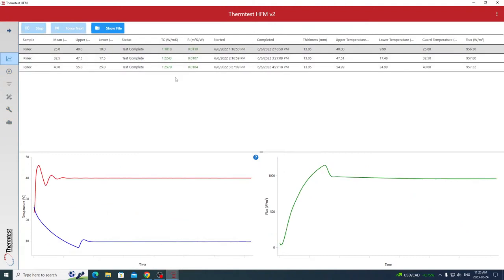So here's Pyrex run at 25 mean, 32.5 mean, and 40 degrees mean. We have values of 1.18, 1.22, and 1.25, and that comes from the resistance and the measured thickness of the sample. And there's your upper plate and your lower plate for each of these, and the guard temperature. Of course, the guard temperature is set to the mean temperature. So you can see that's why we're getting high confidence values.